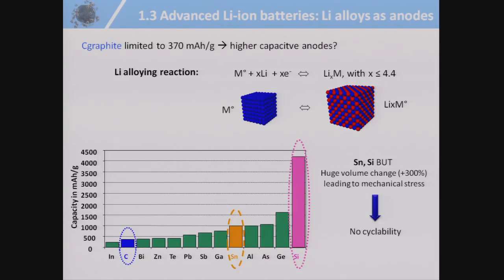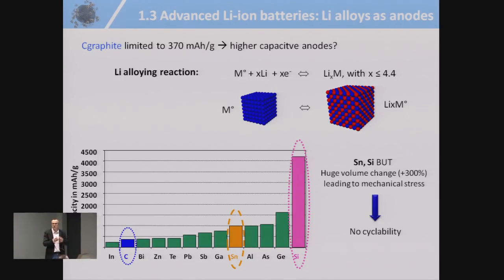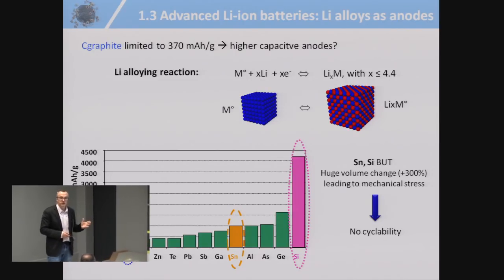So you charge the battery, you discharge the battery. You do 3 cycles. Mechanically speaking, these materials are not stable at all. And this explains why, to this day, there is a huge research effort on silicon. Panasonic has launched this new silicon generation battery, but it's very tricky to solve.